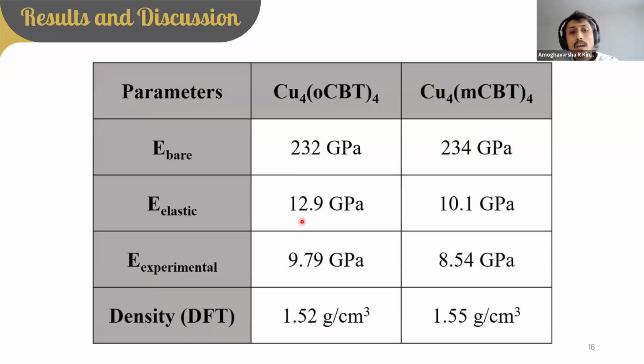That is giving the observed mechanical properties, which can also be seen in computation, where we get 12.9 gigapascal for copper 4 OCBT and 10.1 gigapascal of Young's modulus for copper 4 MCBT. These values are quite high when compared to experimental values, but they follow the same trend that the less dense material has higher Young's modulus. These are just DFT calculated densities.